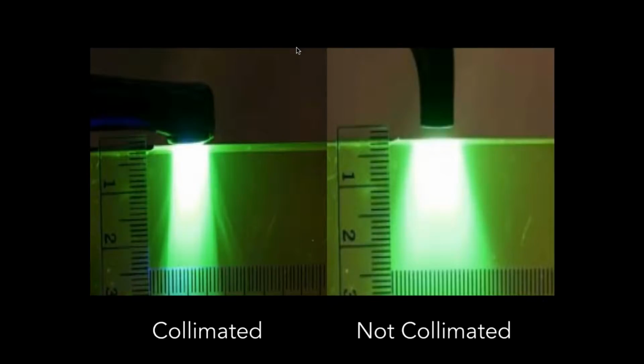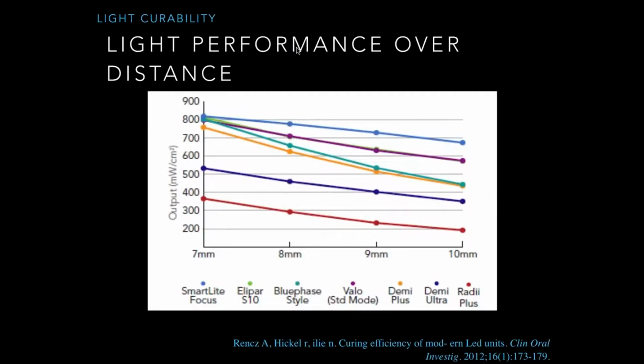As you can see here, not all curing lights and beams are created equal. Take a good look at your light and see how direct and collimated your beam is. You need a good focus for good curing, and especially need a good quality curing light when curing the proximal box or bulk materials. Always remember, a bulk fill requires a bulk cure. One of the most challenging aspects of any restoration is delivering enough energy to light cure the resin composite in deep preparations. All curing lights experience an energy drop-off that decreases the amount of energy delivered to the restoration over distance, and the amount of energy lost varies among curing lights.